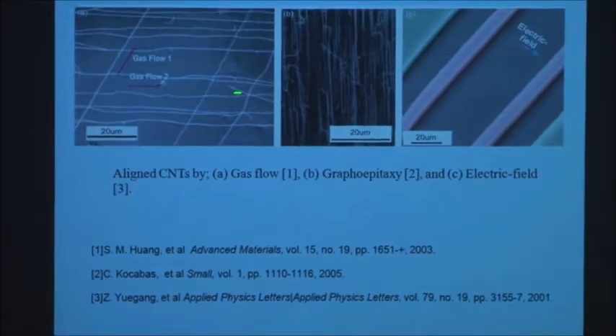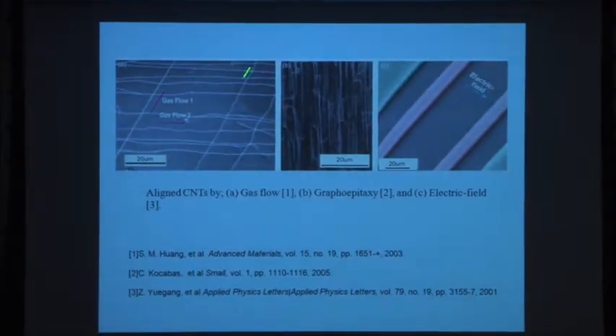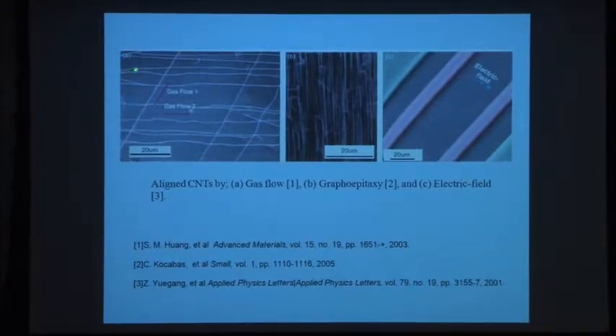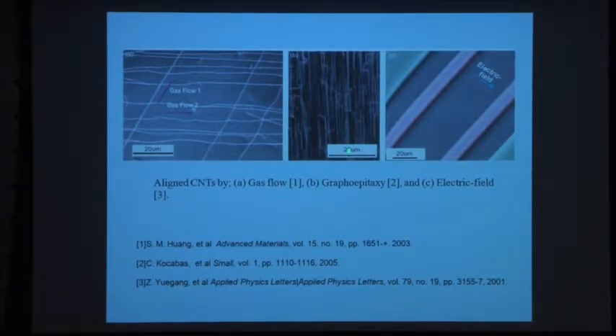But there's been a lot of effort over the past few years on controlling, as I say, position and direction in which they grow. Here's one way. Another way you can do them, instead of applying a field, you can control the gas flow. And in controlling the gas flow, you can end up with like a tartan pattern. Change the gas flow, you change the direction in which they grow. You can get graphoepitaxy, get little ledges where they can grow on preferentially.